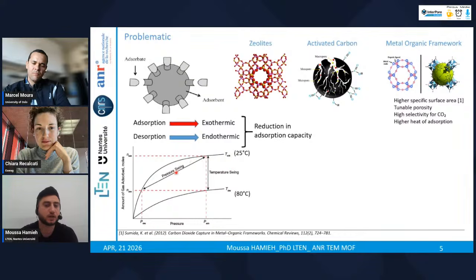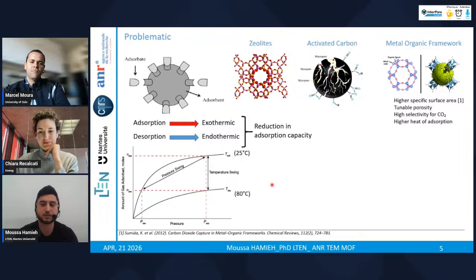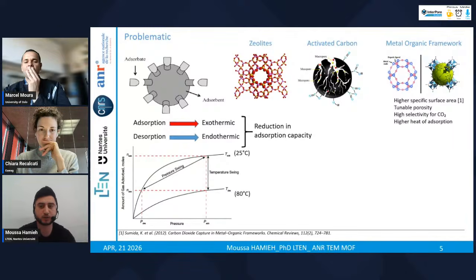Here we see two isotherm lines, one at 25 degrees and the other at 80 degrees, with something called temperature swing. This is temperature swing adsorption, the process to adsorb and desorb in our case. What does that mean? TSA, or temperature swing adsorption, means that we adsorb at low temperature, for example at 25, and we desorb at high temperature, for example at 80 degrees. And to desorb, we need heat, so we heat our sample to reach the temperature suitable for the desorption, and then we desorb the CO2 already adsorbed during the adsorption phase.